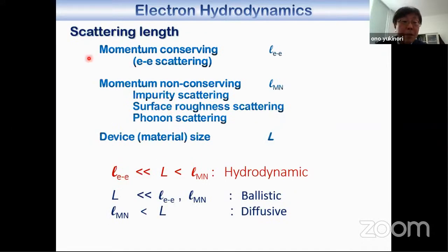However, this can be observed and can be applied to electron devices if this inequality is satisfied. Here, the LEE is the momentum-conserving electron scattering length. And also we have a competing momentum non-conserving scattering process, such as impurity, surface roughness, and phonon scattering. And we denote the scattering length of them LMN. Another important parameter is the device size. The hydrodynamic effect can be observed if the electron-electron scattering length is much shorter than the device size, and also the unwanted momentum non-conserving scattering length is larger than the device size.